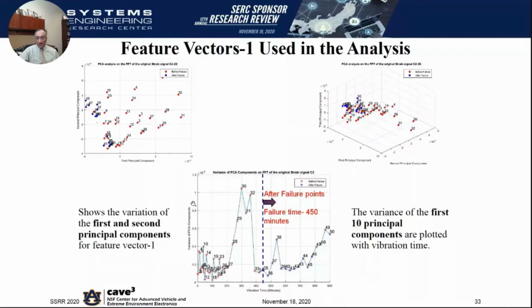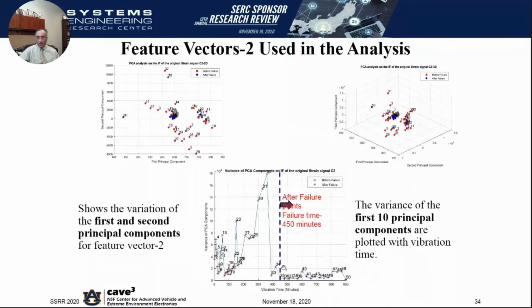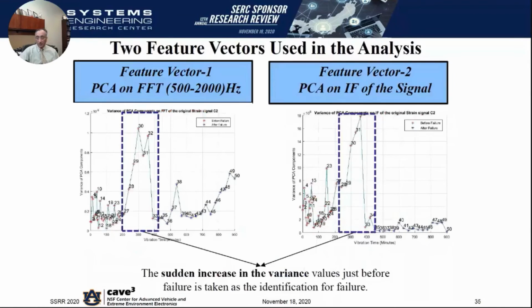Second thing that one can see is that if one looks at the variance of the PCA components, the variance increases tremendously prior to failure. So the dashed line is prior to failure, and the variance increases tremendously prior to failure. So that's extremely helpful. The variance is a good indication of impending failure. So similar trends in feature vector 2, occupy different parts of the feature space, similar increase in the variance prior to failure. So feature vector 1 and 2 work extremely well in this particular case.